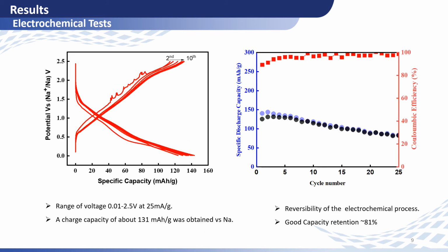Concerning the galvanostatic test, our material was tested in a half sodium electrochemical cell between the potential window 0.01 until 2.5 volt at a current density of 25 milliampere per gram. It delivers an initial charge capacity of 131 milliampere hour per gram and a discharge capacity of 140 milliampere hour per gram. Also, it presents a good efficiency of 98% after 25 cycles at 25 milliampere per gram.